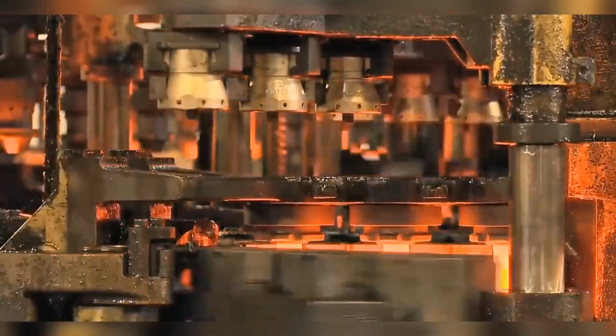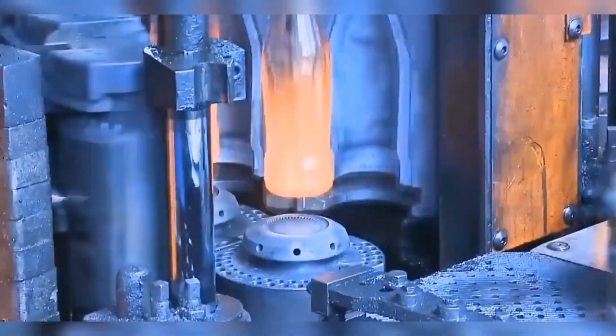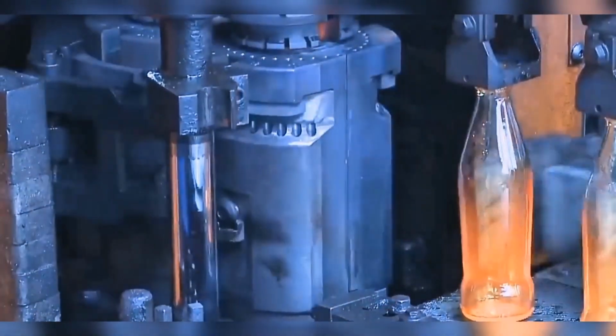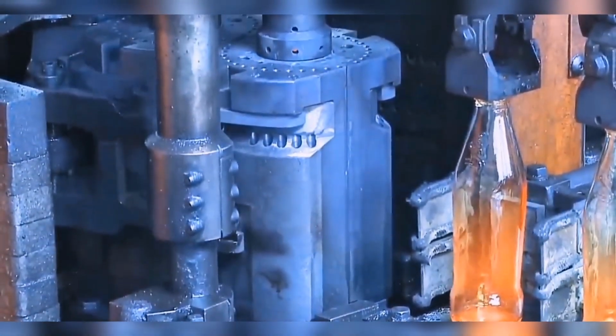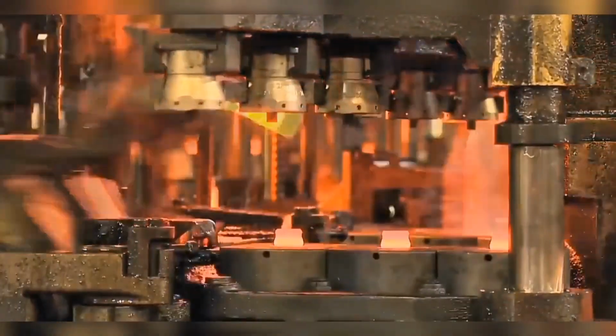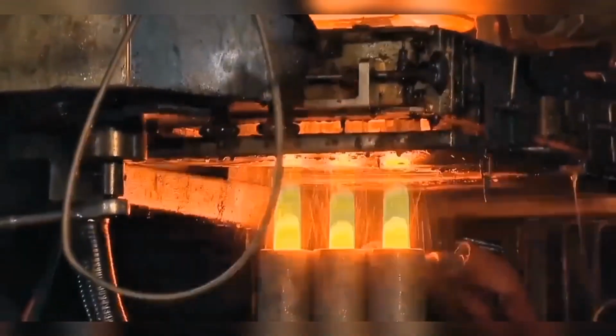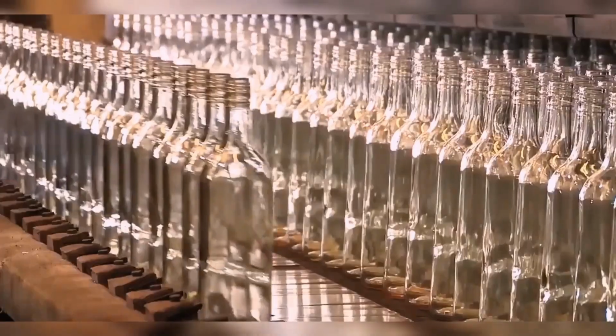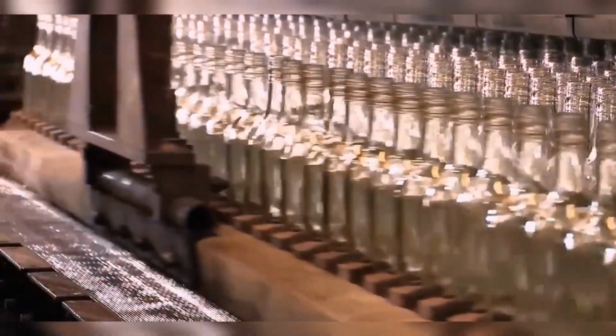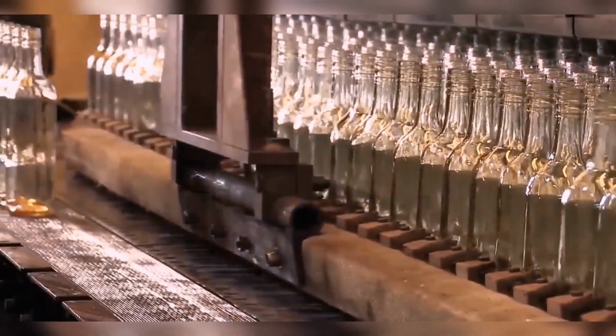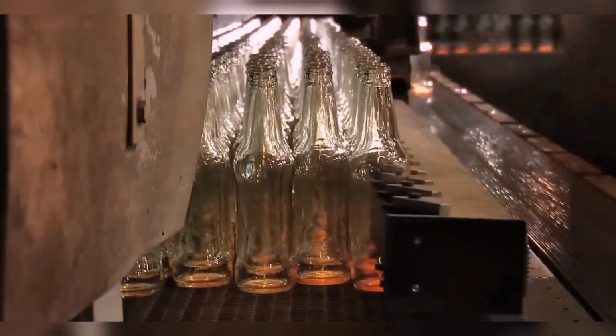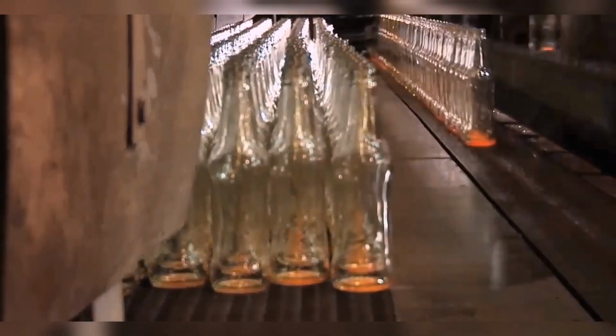Molds, neck finishing, and takeout. Parison and final molds are water-cooled tool steel pieces that dictate shape and texture. Neck finishing and reheating steps may be used so that the finished threads and lips meet dimensional tolerances. After forming, automated grippers take the hot containers to the lehr for annealing. Some high-end lines include hot end coatings so as to improve abrasion resistance before the lehr.